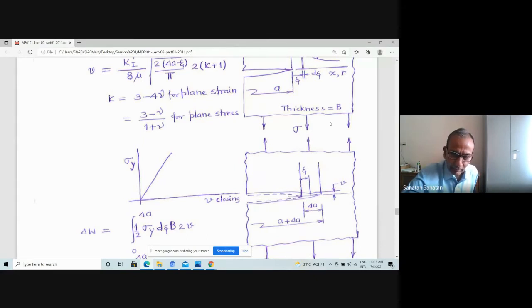It was closed here, but now it has opened up by a distance V on each side, therefore 2V. So when your crack is extending, this portion of the material is getting load free, so it becomes stress free, and in the process it also gets displaced by 2V at the distance xi from the crack tip. So can we calculate the energy, the work done? The crack at a point xi had 0 displacement before the crack extension, but after the extension it has become 2V. So load is reducing to 0, but displacement becomes 2V.